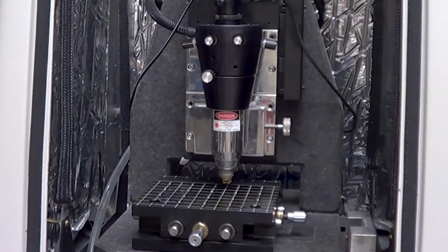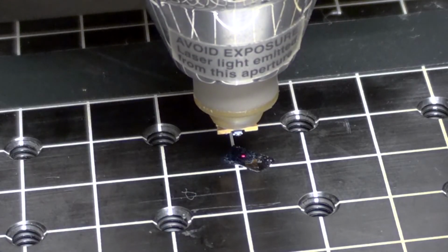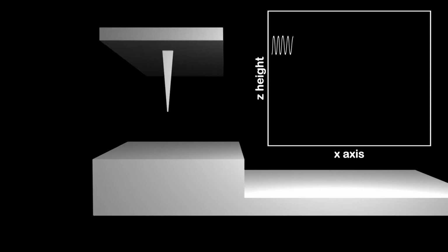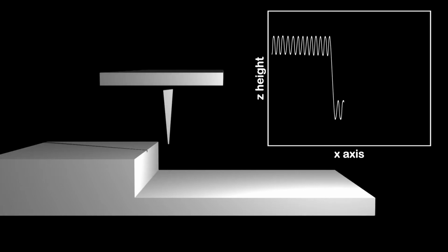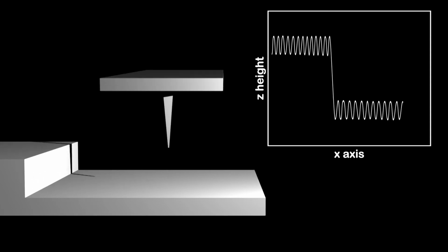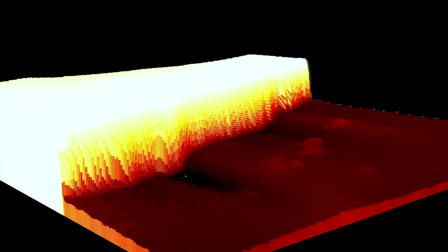While waiting for the experiment to finish, we can measure the initial thickness of the film. We make a few razor cuts in the piece that was set aside earlier in order to provide a baseline for the thickness measurement. The AFM works by vibrating a cantilever with an extremely sharp tip and scanning back and forth across the sample. The features of the sample cause deviations in the cantilever vibrations, which are recorded as changes in height. Once the scan is complete, we essentially have a topographical map of the sample. The thickness can then be measured using the change in height between the film and the wafer.